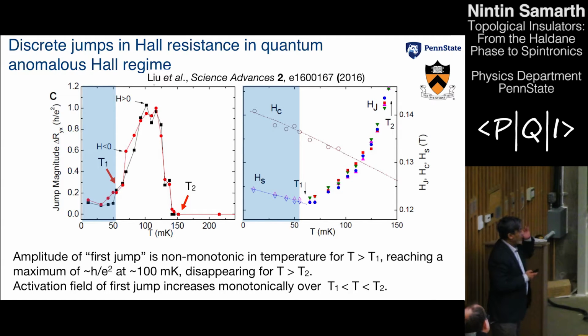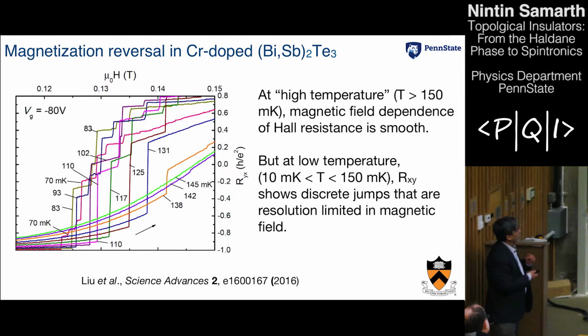So the way to characterize this data is to look at two parameters. One is that at any particular temperature, you can look at the height of the jump, right? The height of the first jump that occurs. That's the first sort of liberation of this domain wall, if you want to take that picture. And the second thing you can ask is, what is the field at which this first step occurs?